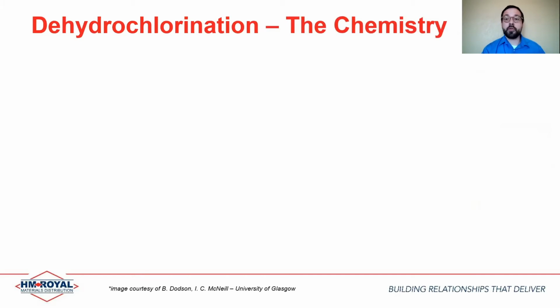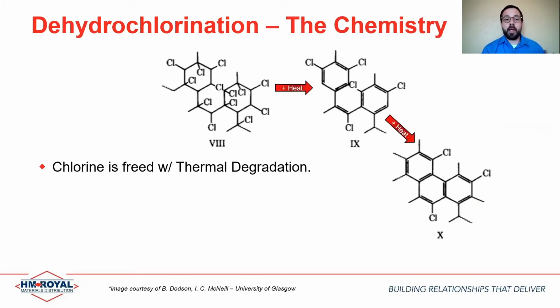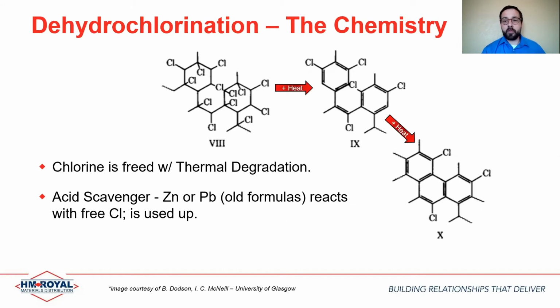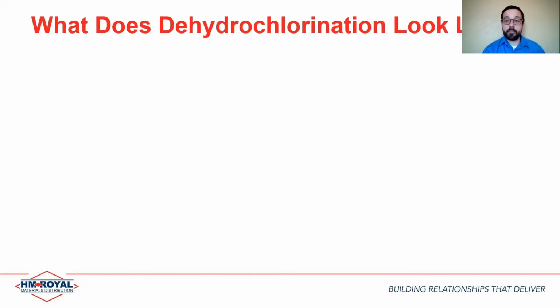So, a quick look at the chemistry. We're not going to dive into this deeply. Essentially, chlorine is freed in this system as a result of thermal degradation. As we continue to expose the system to heat, the acid scavenger, be it zinc, like in our formulas, or lead in some outdated formulas, is going to react with this chlorine, and it's going to be used up. The zinc and the lead is going to combine with the chlorine, and it's no longer going to be free and available to scavenge acid. As a result, HCl is going to form and corrosion is going to occur at the metal surface.